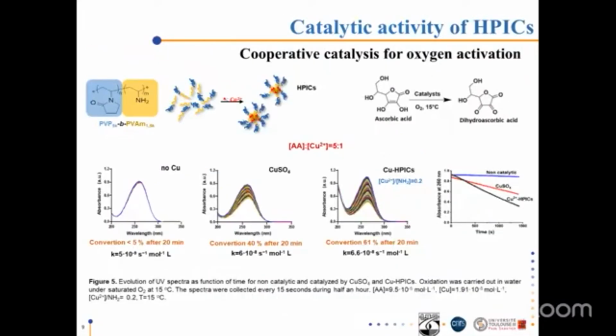At the next stage of our experiments, we evaluated whether the obtained HPICs could be applied in catalytic processes. For this purpose, we selected ascorbic acid as a model substrate and studied its oxidation by atmospheric oxygen in the presence of copper HPICs. The oxidation was carried out with a copper to substrate ratio of 1 to 5 in water under saturated O2 at 15 degrees.